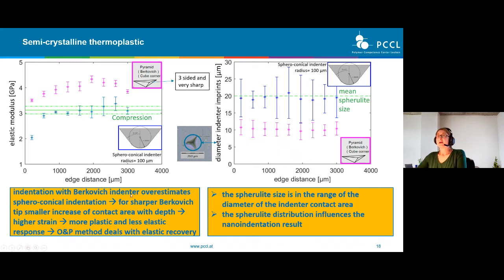And this is because when we indent with Berkovich, the Berkovich has a sharper tip, and here we have more increase of contact area with depth. This causes a higher strain, and therefore we have more plastic and less elastic response. And as I told you before, the Oliver and Pharr method deals only with elastic recovery, and therefore Berkovich overestimates here the spheroconical indenter tests.